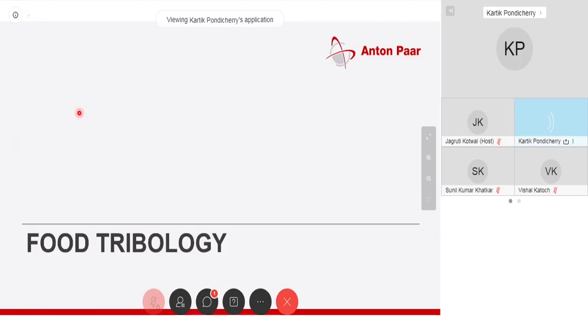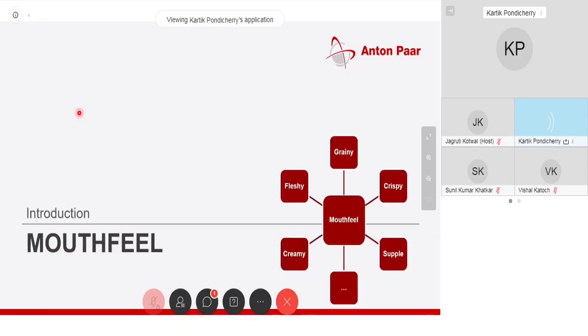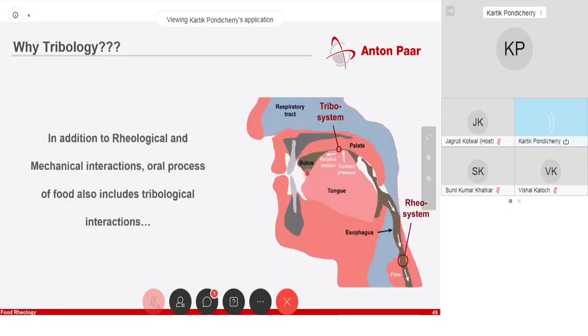With that, we come to the next part, which deals with food tribology. What exactly are we looking at? This is about the mouthfeel again. Why rheology and why tribology? In our oral cavity, you have multiple processes going on — bolus forming, mechanical properties during biting, and then when your bolus passes between your tongue and the palate, it becomes an actual tribosystem. A tribosystem is when you have two interacting surfaces with or without a liquid or fluid in between. We use a glass ball rubbing against three PDMS (polydimethylsiloxane) pins, and you need only 1.5 to 2 milliliters of sample. This whole thing sits on a rheometer and then we run the test.